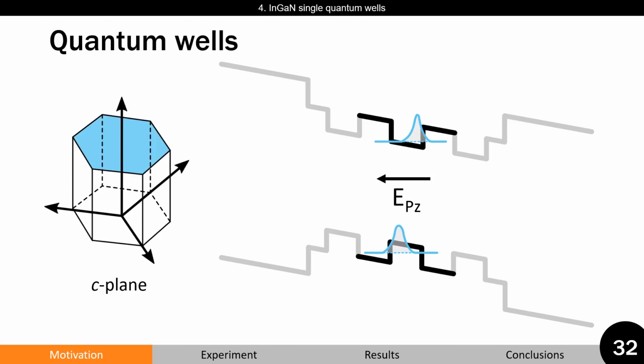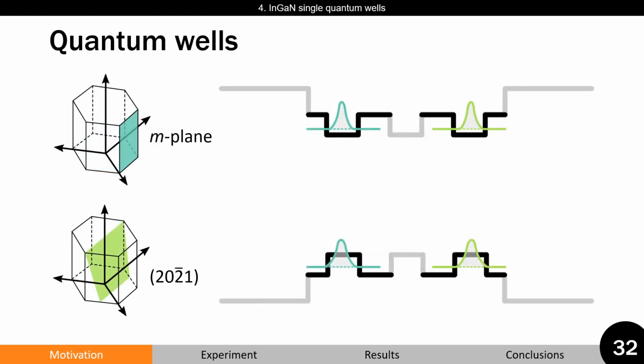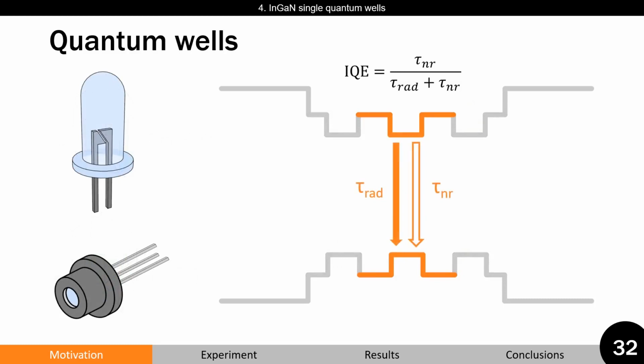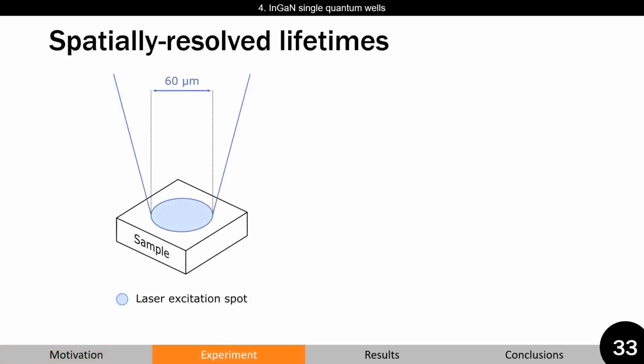In order to combat this, quantum wells could be grown on non-polar m-plane or semi-polar planes, thus increasing the overlap between wave functions. Before growing a complicated device with multiple quantum wells, it is useful to investigate a single quantum well. Two of the most important parameters are radiative and non-radiative lifetimes, as these define the internal quantum efficiency of a structure. These values are usually evaluated using conventional far-field spectroscopy techniques.